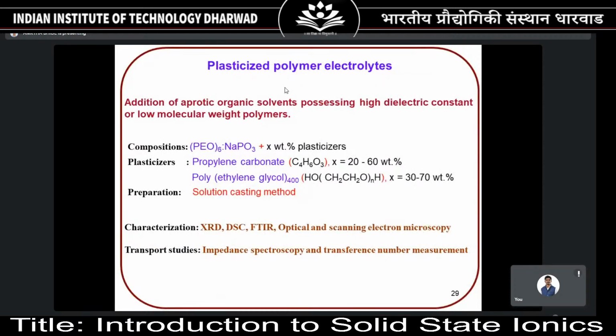Plasticizer means something which gives a lubricant kind of effect. Unlike the ceramic fillers, which are solid, in this case we are adding organic solvents like propylene carbonate, ethylene carbonate. If you consider polymers, low molecular weight polymers, polyethylene glycols, having molecular weight about 400, 600, are in liquid form. These low molecular weight polymers are in liquid form, or propylene carbonate also, which is again a liquid organic solvent. You add these materials in different weight percent into the matrix.